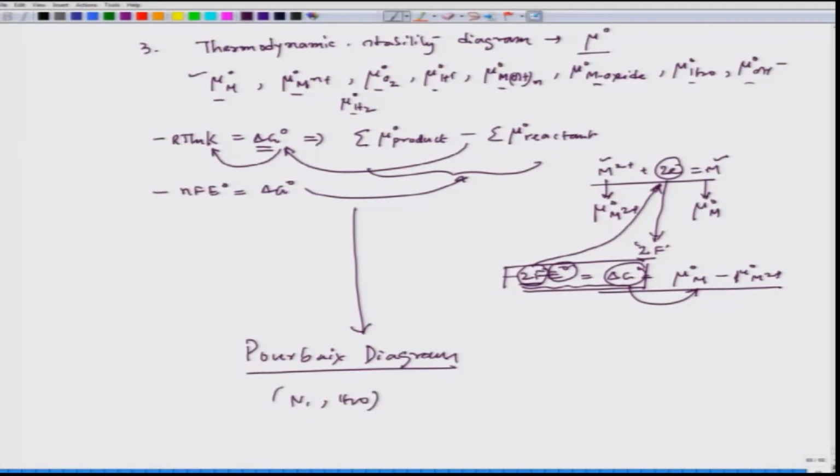So, in our next lecture, we will try to work through one example in the nickel system, the nickel H2O system. We will try to see the Pourbaix diagram, and we will start from the chemical potential of different species, and we will end up getting that diagram, and then we will see that yes, in this position, I will get metal remaining as metal. In this position if I go, I will get metal ion formation or corrosion, or at a certain region we might get metal hydroxide which will settle down. So, we consider it to be a passivating zone.